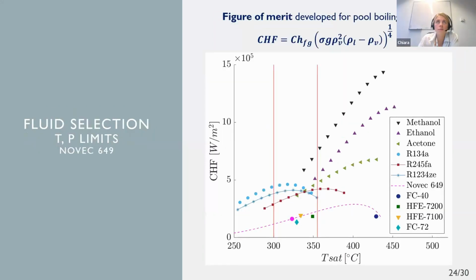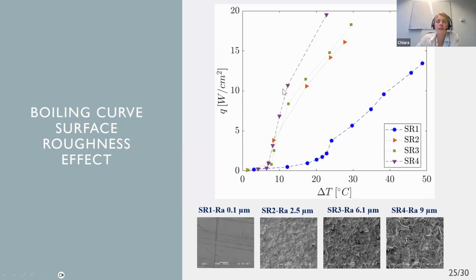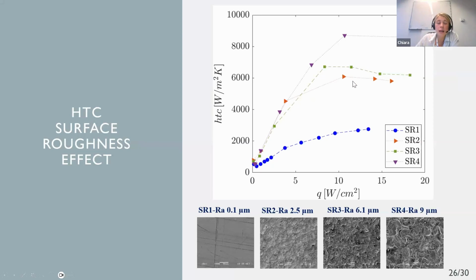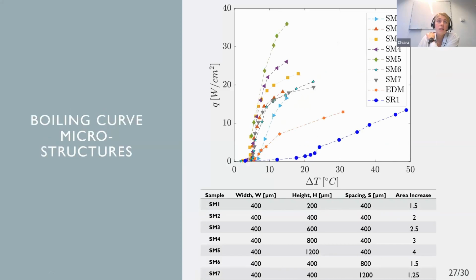Yes, so of course, we had to run an uncertainty analysis. The uncertainties come from the propagation of error. For the heat transfer coefficient, we had a maximum uncertainty of 10 to 12%, depending on the conditions, because this varies with temperature and power. On the critical heat flux, so on the Q, on the limits, we had a maximum uncertainty of around 4 to 5%.